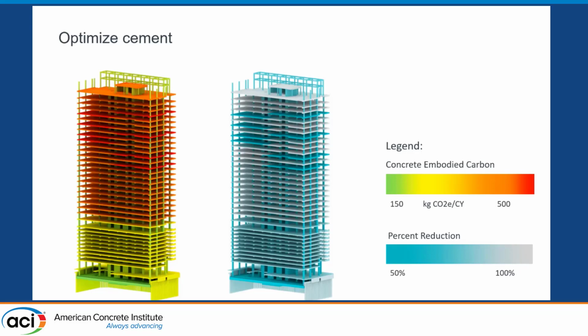And then additionally, looking at cement reduction, cement may be reduced in some regions by specifying higher quality aggregate or using less water. For example, I know on the West Coast, in some California regions, it's the aggregate that really limits the strength of the concrete mix. And they have been, in some cases, shipping down aggregate, I think from the Pacific Northwest or British Columbia, in order to increase the strength of those concrete mixes and thereby reduce the cement. And the carbon emitted by the transportation process is actually less than the carbon that it would have taken to increase the strength by adding cement to the mix. So clearly, optimizing Portland cement usage is an important strategy in reducing the carbon impact of concrete mix design.